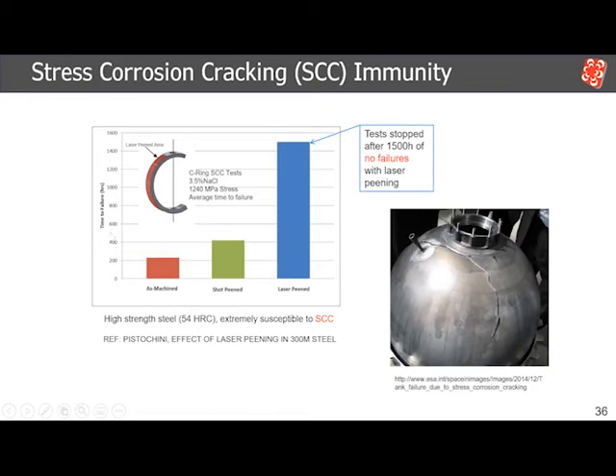So let's talk about this example here. A common way of testing stress corrosion cracking is using C rings or U bends. And in this specific example, we have susceptible material, which is 300M steel. And we're placing it in a corrosive environment, which is sodium chloride. And we're applying tensile stresses, 1240 megapascal stress. So we have all 3 conditions to cause stress corrosion cracking in this part.